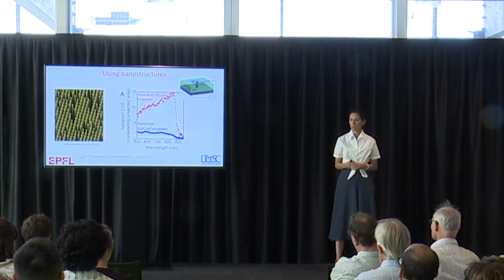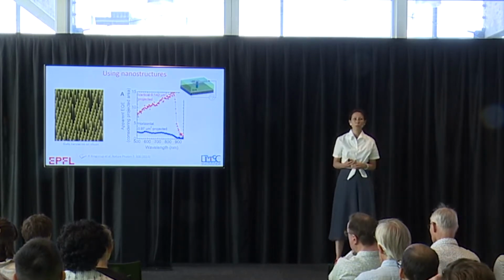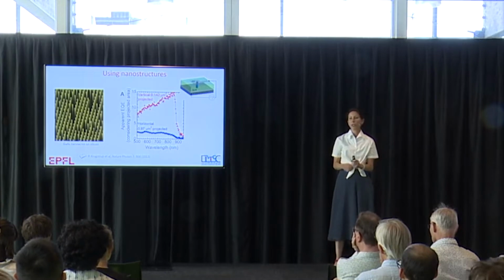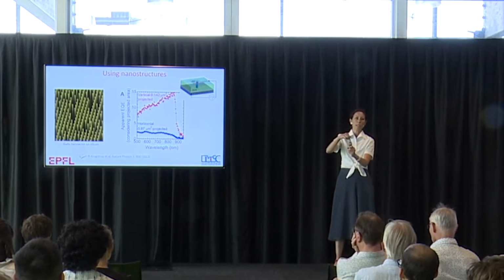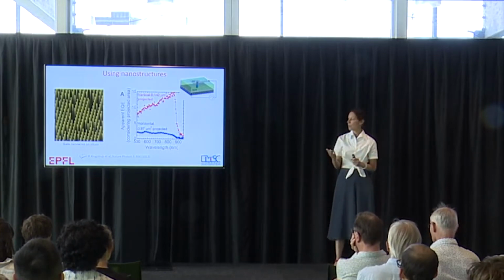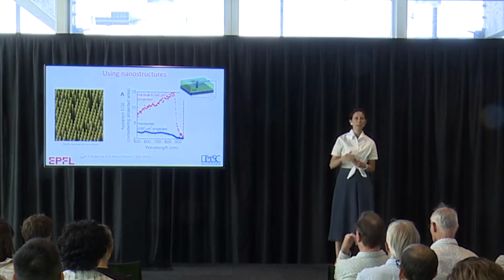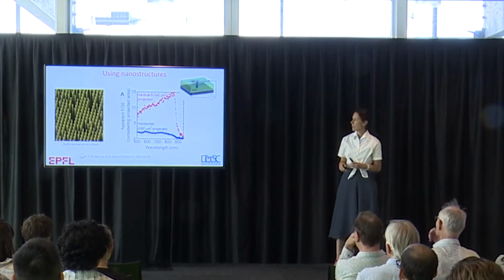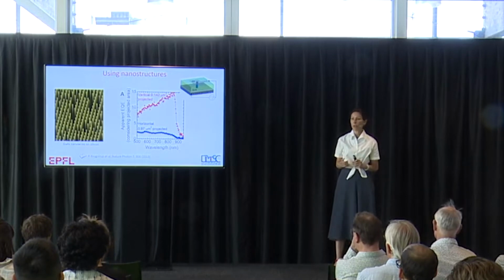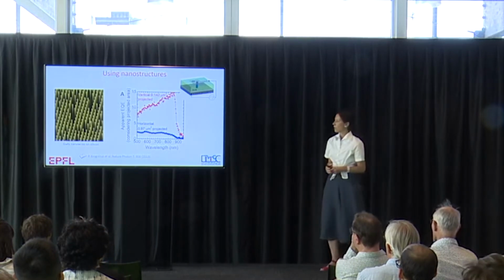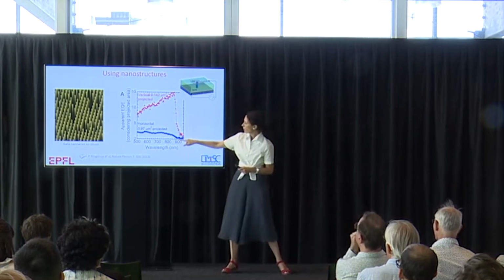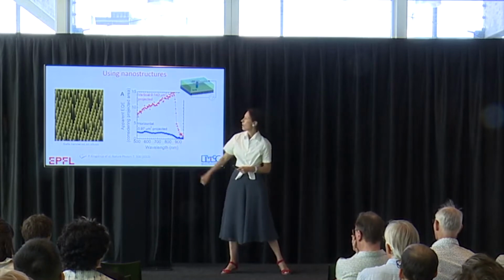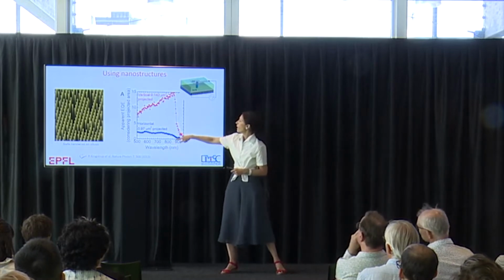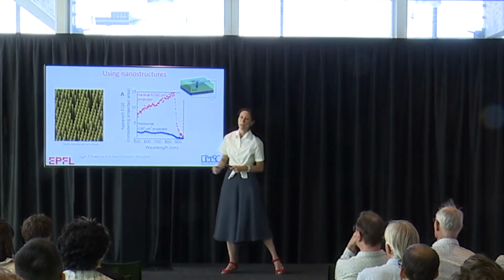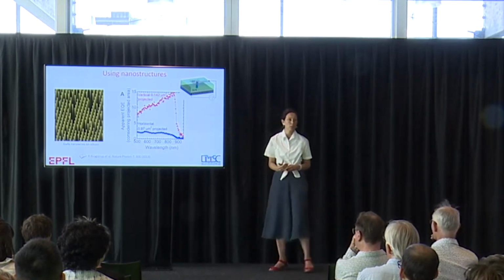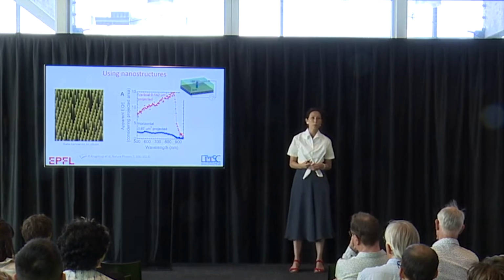What you see here is the external quantum efficiency, measured as, for a nominal photon getting on the wire, how many electron hole pairs you create, and from the same batch you also have the wire that is lying on the substrate. What you see is first you have very different numbers, and also the shape of the curve is very different. You see here that with the lying nanowire you have very low absorption close to the band gap, while when you have a standing one you have a very high absorption. The highest absorption is close to the band gap, which is not typically what you have in semiconductors. You usually have very low absorption close to the band gap.